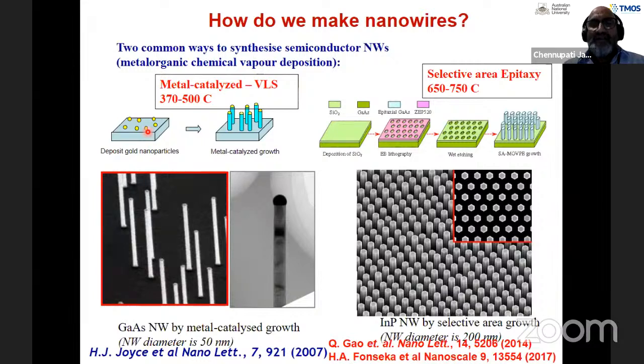So now if you put this wafer, which is gallium arsenide, for example, with gold nanoparticles into an MOCVD reactor, metal organic chemical vapor deposition, there's also an alternative technique called molecular beam epitaxy. You can use either of the techniques to make nanowires. You put this into the reactor and heat it to somewhere between 370 to 500 degrees Celsius.